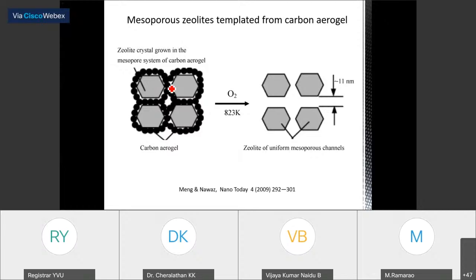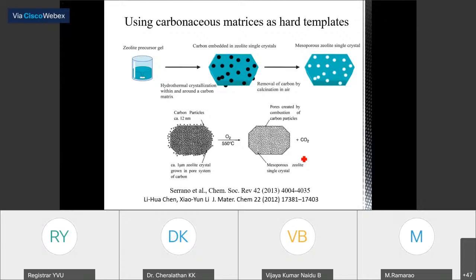And not only that, even you can use carbon aerogel. When you synthesize your zeolite inside the pores of carbon aerogel, then you can reduce the size of the zeolite crystal. And when you have this kind of uniform crystals, what will happen? There will be interparticle porosity. So they will be falling in the mesoporous range. So it can be called as a mesoporous zeolite. Not only that, you can introduce some carbon into the zeolite crystal and finally remove the carbon. Okay? So when you heat in the presence of oxygen, what will happen? All the carbon will be removed from the zeolite after formation of the zeolite. Then you will end up with a zeolite crystal with additional porosity.